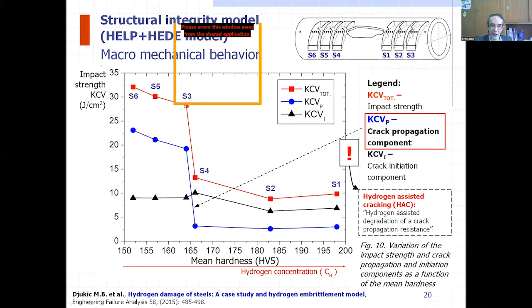And as you can see, for S3, for example, we have a relatively good impact strength. This is the total amount of impact strength in red color. This is the crack propagation component of impact strength in blue color, and you can also see the crack initiation component in black. In the case of S3, we have a relatively good value, while in the case of S4, we have a very sharp drop in total impact strength, but also a very sharp drop in crack propagation strength, which became lower than the crack initiation strength.